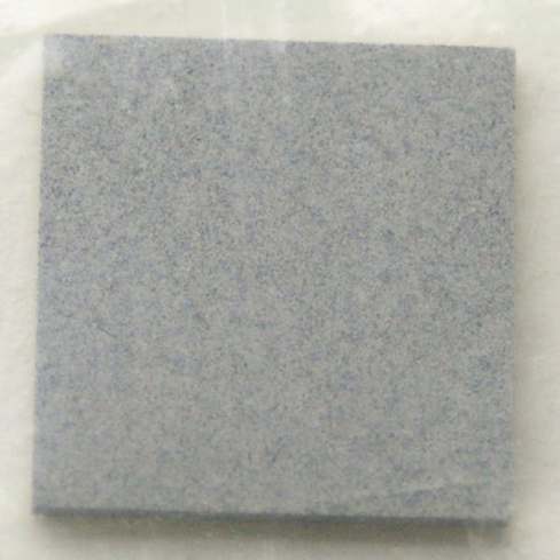Production. The material is prepared by heating powdered silicon between 1300 degrees Celsius and 1400 degrees Celsius in a nitrogen environment: 3Si + 2N2 → Si3N4. The silicon sample weight increases progressively due to the chemical combination of silicon and nitrogen.